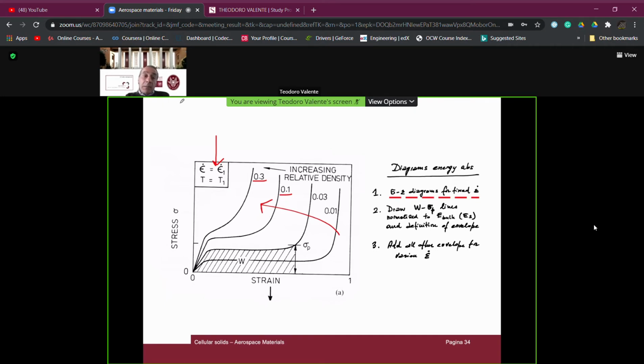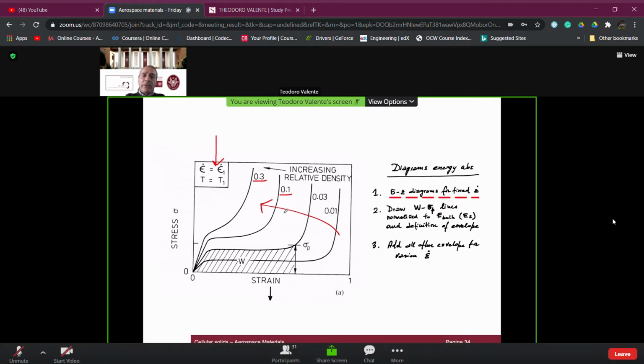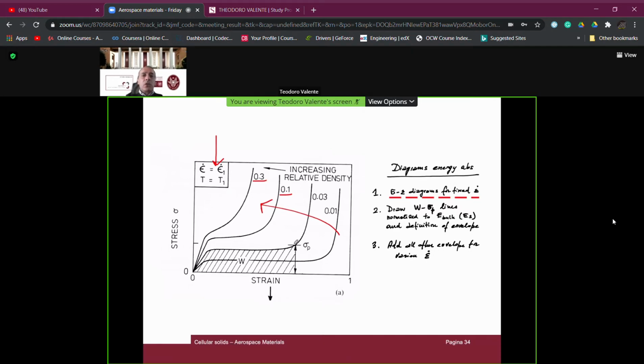stress-strain diagrams in compression, again for a fixed value of the strain rate. And then, with a fixed value of the strain rate, we have diagrams having the mass density as a parameter. So we can identify for each value of the mass density the peak stress, the one corresponding to the plateau in the case of an elastic foam, or the one which, due to buckling, I remember, is